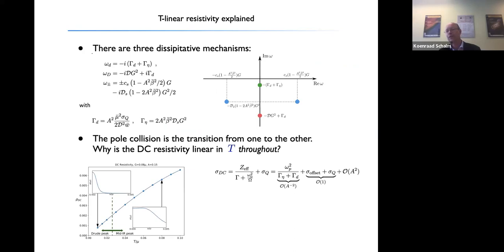Now, remember this larger context of the story that I wanted to explain. What I wanted to explain is that I have this very robust, essentially linear in T resistivity, that as I increase the temperature, I have a real change in the dissipative mechanisms in this behavior. And this is precisely what happens in this particular case: it's the Drude-like pole, or maybe with a small contribution of this guy, that controls this behavior. But once I have the two poles collide, it's a much more complicated system where the objects dissipate through.